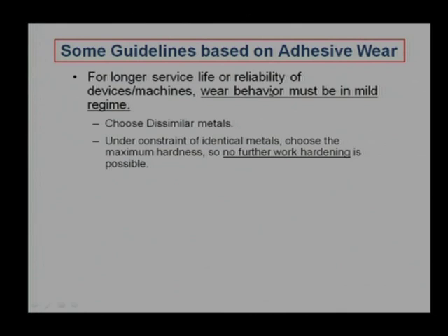The first guideline says that for a longer service life or reliability, if you are really aiming for a longer service life or reliability of a machine, always aim for the mild wear regime. In this case, mild regime means the wear particles coming out of the material or surfaces need to be much smaller in size, less than 1 micron. We are talking about the macro level; of course, if we talk about micro components or nano components, then the wear rate and the particle size will decrease in that same order.